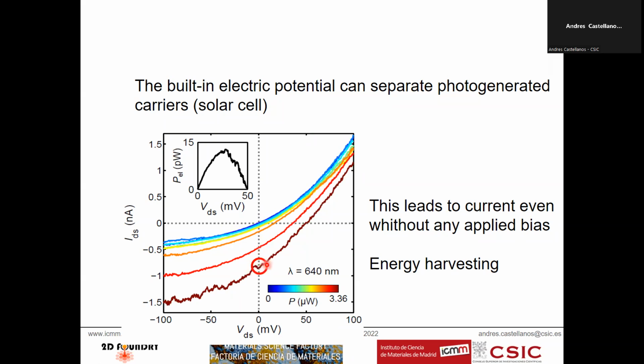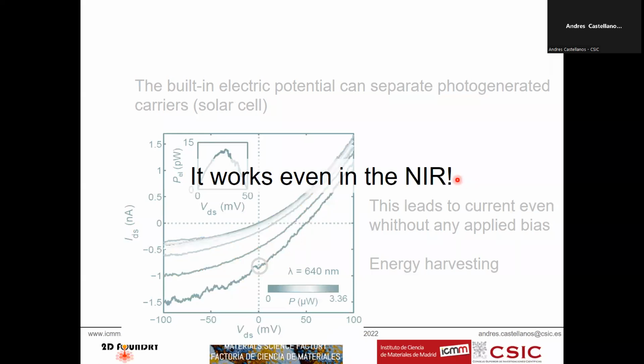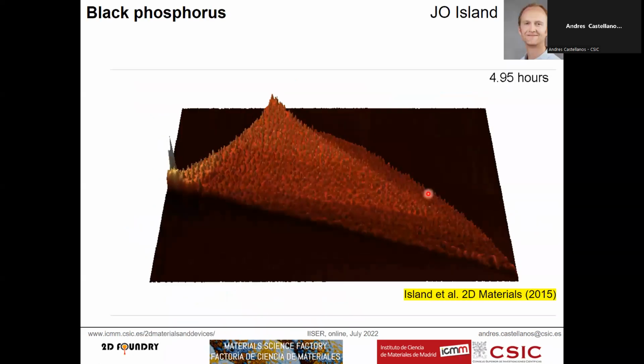Okay, so this can be used for energy harvesting, and it can even be used in the near infrared because black phosphorus is sensitive to wavelengths in the near infrared and even to the short-wavelength infrared regime. So it reacts to light up to 3.2 microns, if I remember correctly.